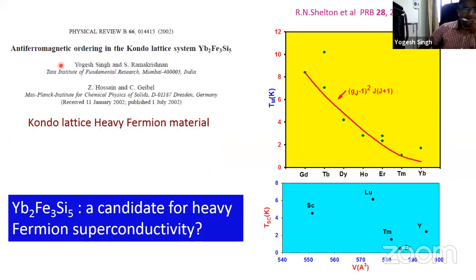So I had started my PhD on this material, trying to address this question. Here I have plotted the ordering temperature versus rare earth, and you see that they scale with the size of the effective moment. What is interesting is that there is also a superconducting transition for many of these materials, not just the non-magnetic materials, but the magnetic rare earths also. So ytterbium from its lattice volume sits in the middle of this. So if I put this here, the ytterbium superconductivity is expected to be at around 4 Kelvin, and this would be a huge temperature for a heavy fermion superconductor. And that is our starting point for looking at this material.